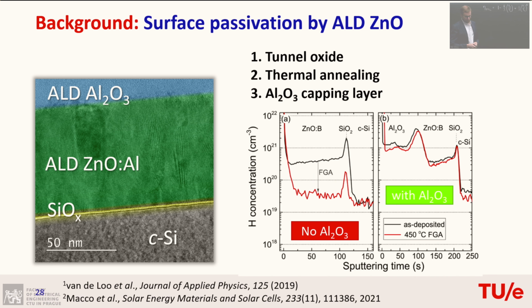Then, what's also important is that we cap our layer. So, as we saw for the aluminum oxide, that is actually hygroscopic, and then everything goes wrong if you don't cap your layer. A zinc oxide is not so much hygroscopic, although it can also react with water in the air. But the issue is more, I think, that we have crystalline grains. So a zinc oxide is just a crystalline material, and the hydrogen, if you start to increase your annealing temperature, can escape along the grain boundaries towards your top surface, and then you lose your hydrogen at the silicon interface.